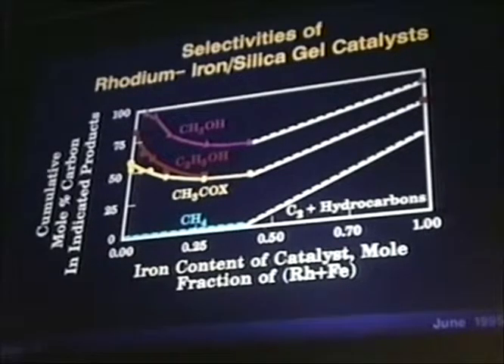While investigating the conversion of syngas to C2 chemicals, one of my technicians would mention on several occasions that he had observed an increase in selectivity to alcohols, methanol and ethanol, as he was running chromatographs. The catalyst was just rhodium on silica gel that we had worked on in the 74-75 timeframe. And depending on the reaction temperature or other conditions, this observation was repeated on several occasions. So that certainly made me curious, and I said, gee, we need to check this out.